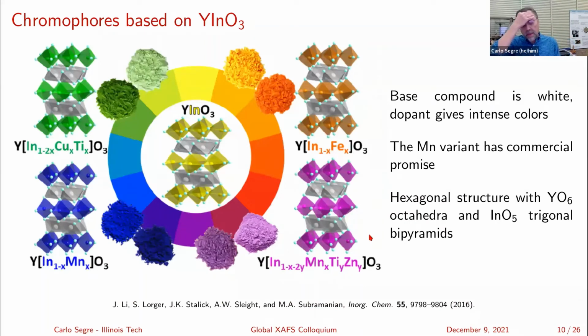All right, so the materials I'm going to talk about are based on yttrium indium oxide, which is a white compound, colorless white. And when you dope it, it gives you some beautiful colors. You can see here a doping with iron in the indium site gives you this very strong orange and yellow. You can get green out of co-doping with copper and titanium. You get purple out of doping with manganese, titanium, and zinc. And then the one that I'll be talking about today is this indium and manganese doping. And this structure is a hexagonal structure. It is not a perovskite.